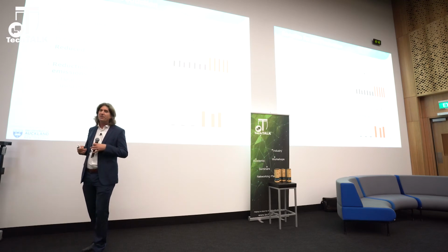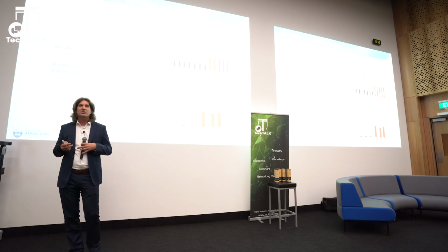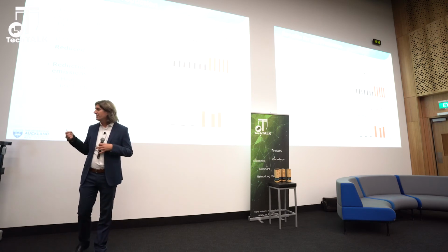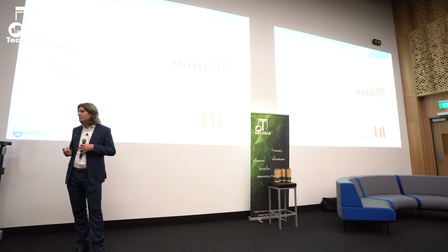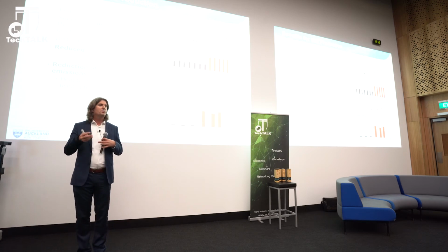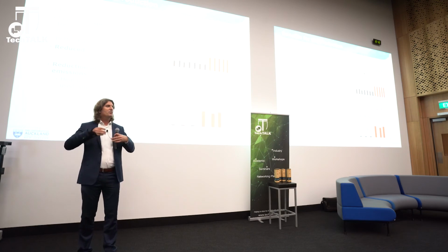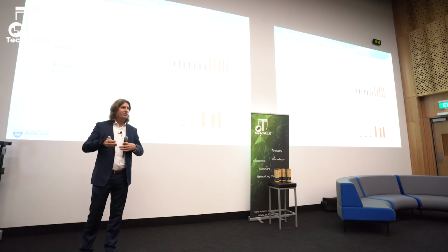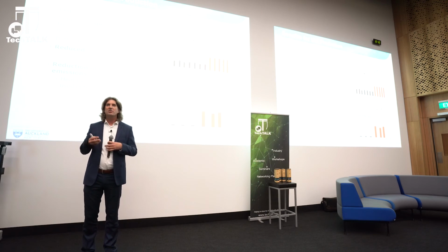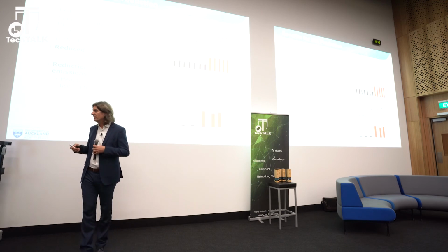And the effect had been that we've been able to produce these products 16% faster. In the other steel grade, even 20% faster. And that by itself is a big number, but it's even more impressive if you think we haven't changed the pickling process itself at all. We just took care that the material arrives in a more suitable condition to the same process.